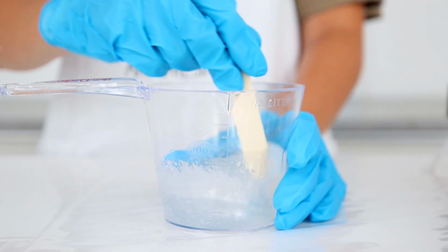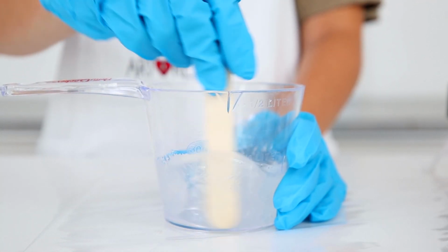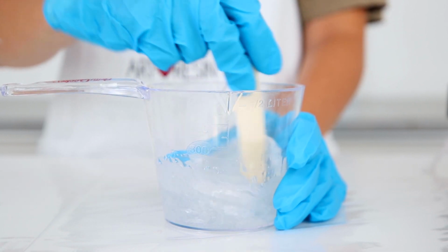Summer often brings high humidity along with the heat. Humidity refers to the amount of moisture in the air, and this can make a difference in your resin's final result. If moisture is introduced into the mix, you may end up with a cloudy look or an oily appearance on the surface layer. This loss of clarity can occur during mixing and pouring or while the piece is curing, so it's important to maintain a consistent humidity level throughout the curing process.